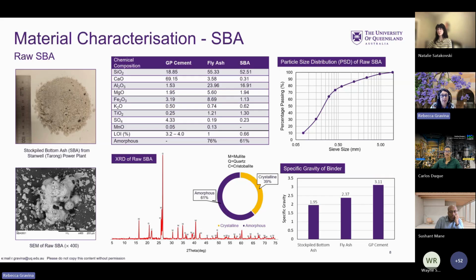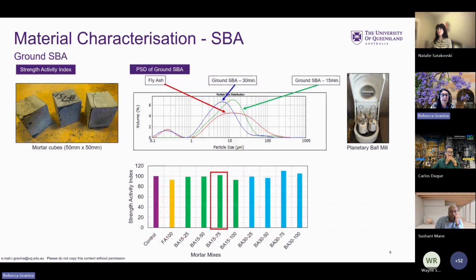So that was the next step that we followed. We looked at using a planetary ball mill to grind that stockpile bottom ash for specific periods of time and try to optimise our mortar mix designs. And we started with a control where we had just your normal cement. Then we had a ratio of fly ash added to the mix design, and then we ran the ball mill for either 15 minutes or 30 minutes, and then added increasing amounts of stockpiled bottom ash.